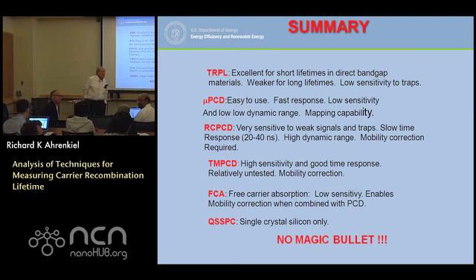Any other questions? So in the case of TRPL, one has an option to look at the decay at different wavelengths if there is emission at different wavelengths. Right. But is there a similar possibility in a PCD experiment? Oh yeah. Over at NREL, I have a tunable system, and we scan the whole wavelength range. And in fact, that's what I did in that one experiment I showed. We have a tunable OPO, and we start out and scan from the infrared into the green and watch the character of the decay change.